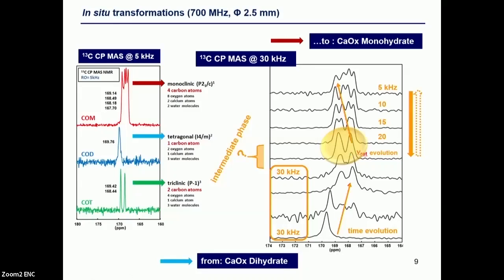And then if you allow the sample to cool, in fact, by decreasing progressively the spinning speed, you end up with the 4 peaks, which are completely characteristic of a monohydrate phase. So in other words, you have monitored in situ, without temperature regulation for sure, the transformation of the dihydrate into the monohydrate. This is completely irreversible: you start from this structure, you spin faster, you end up again with this intermediate phase, and if you go back down, you will retain the structure of the monohydrate.